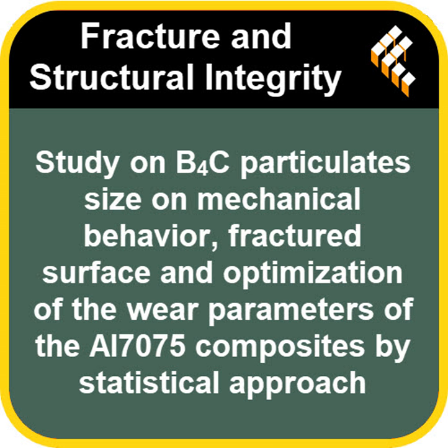Smaller particles, harder material. What's the mechanism? Why does that happen? Well, imagine trying to push something through a tightly packed space. If the obstacles are small and numerous, they resist that movement more effectively, right? Nanoparticles act similarly. They effectively hinder the material's ability to deform or flow under stress. They also create more interfacial area, more connection points with the matrix, which helps the composite absorb external loads more efficiently. Okay. Larger microparticles, on the other hand, while they might help with ductility, showed lower resistance to that kind of dent deformation.